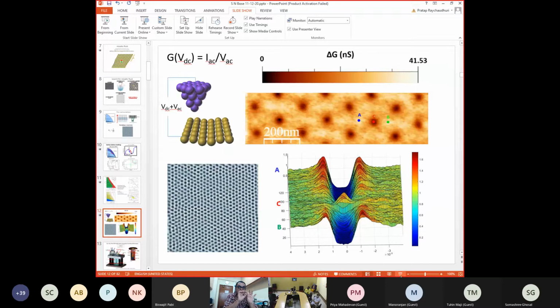The tunneling conductance of normal metal to normal metal and normal metal to superconductor has a slight difference. Therefore, if I keep rastering the tip and recording the conductance at all points here, wherever I have a vortex, I will see that the conductance is slightly lower, so it will manifest as a minima in this conductance map. From these minima, I can find out where the vortices are, and that is how such an image is recorded. You can do this over a larger area, and then you will get a vortex image like the one I am showing you here in this corner.